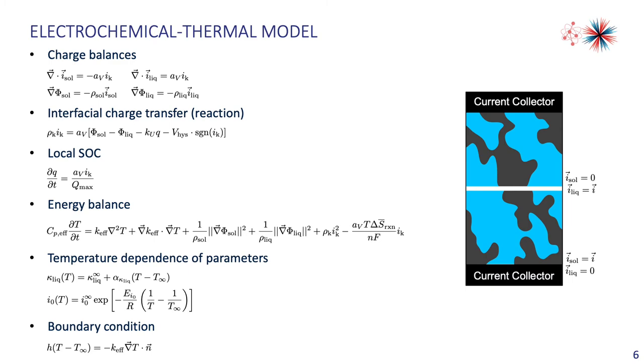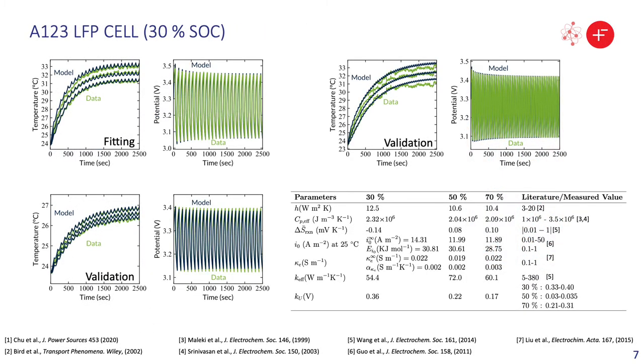And the result of all this is an extracted parameter set that can predict different square waves. We trained the model with the most strenuous square wave which had an amplitude of 4C and a period of 100 seconds.